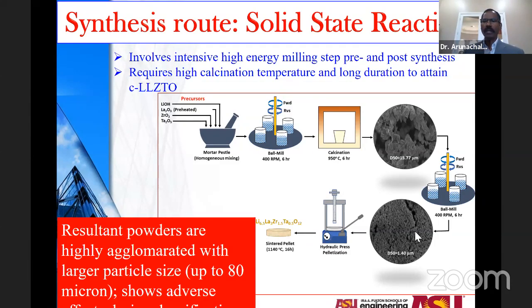So to have finer particles, the initial calcination would give a stable structure, whether it is tetragonal or cubic, but the goal is always to get to cubic. At the same time, what is important is to make the pellet highly dense. So the relative density should be at least more than 95% to have absolutely no growth of dendrite if the electrolyte pellet is fabricated into a full cell, whether with lithium metal, and also the LCO cathode or other cathode materials.